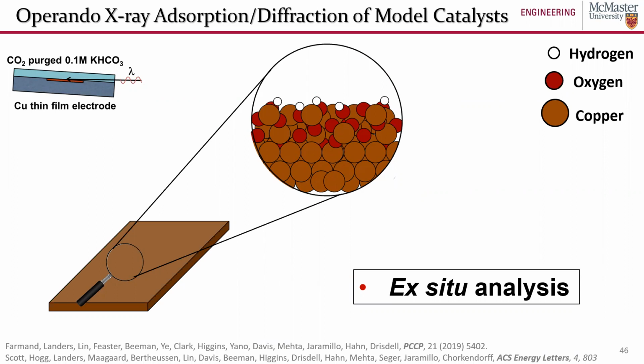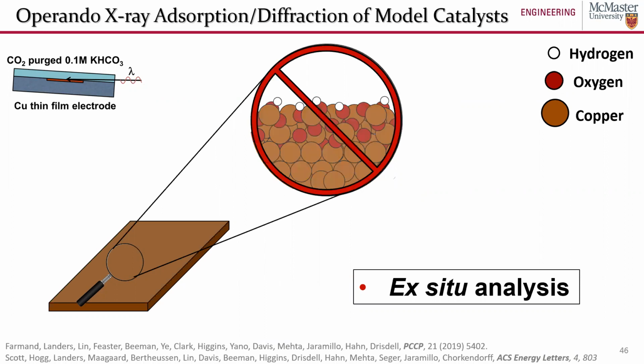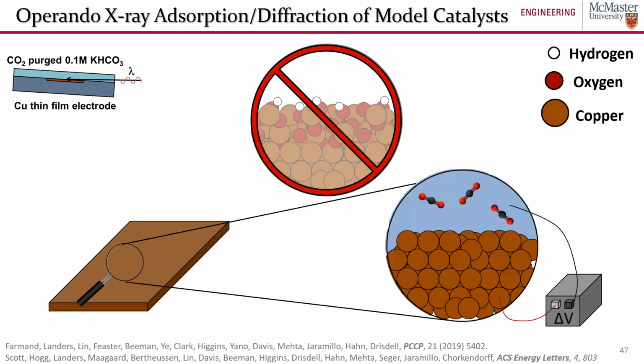But when you actually do the in situ or the operando measurements, what we found is that there was no copper oxide present at all. It was all metallic copper. So what that told us is that the CO2 reduction was occurring on metallic copper. And this was the only way we could get conclusive evidence of what the surface of those materials looked like under reaction conditions: by doing it via this in situ or operando characterization enabled by one of these miniaturized reference electrodes that I talked about.